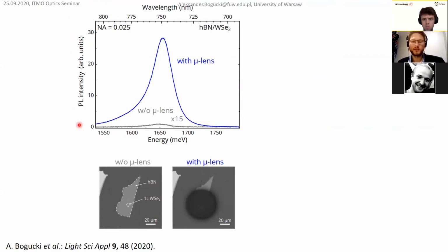So, to see how it works in real life, this is the plot of photoluminescence intensity collected only with one lens, obtained from a transition metal dichalcogenide flake. This is tungsten diselenide, a heterostructure, so it was covered with hexagonal boron nitride. And this gray curve represents the photoluminescence multiplied by 15 without microlens. As you can see, it's barely visible, so you can't see anything. And with microlens, you have a pretty nice signal. It looks like that. As I mentioned before, in size, it's 5 micrometers of our flake, like here, covered with this hexagonal boron nitride.